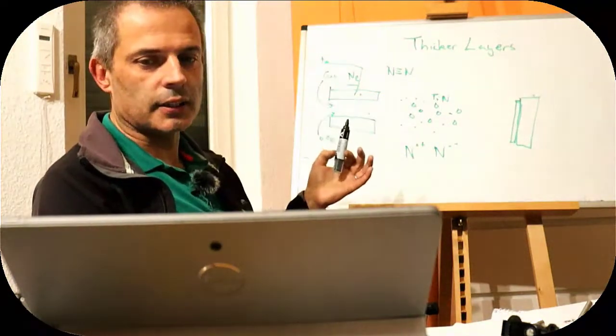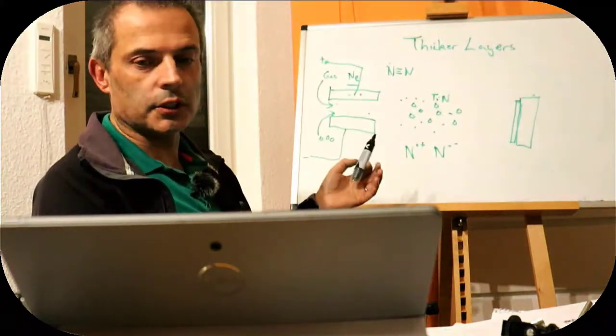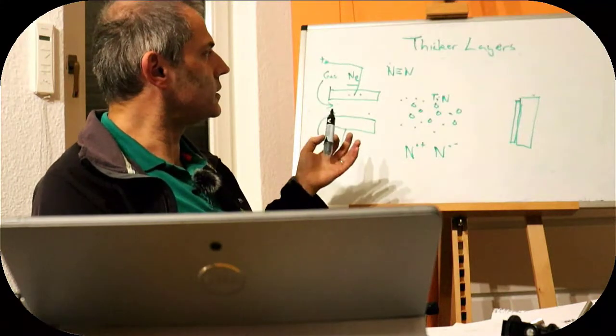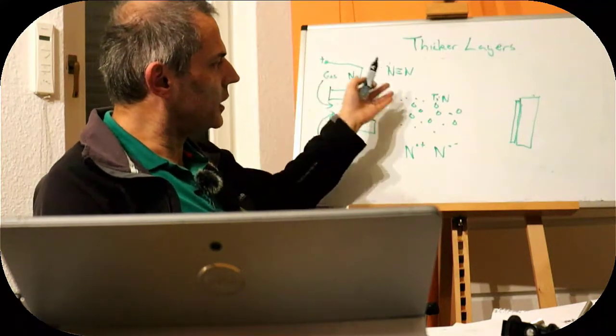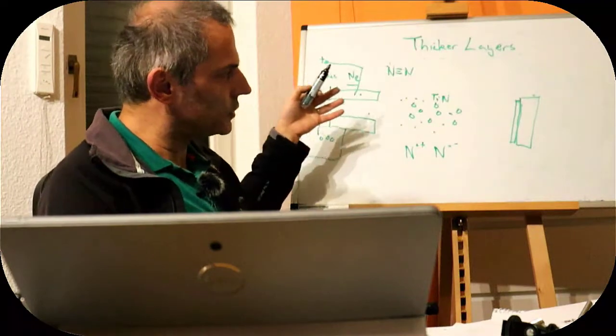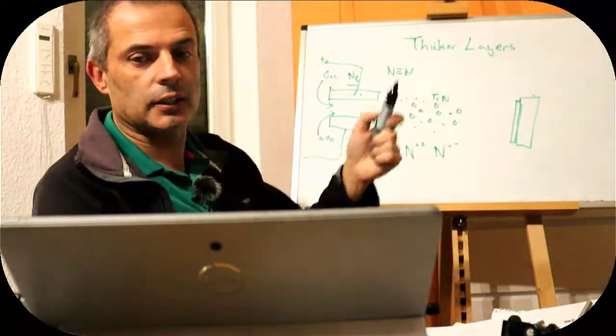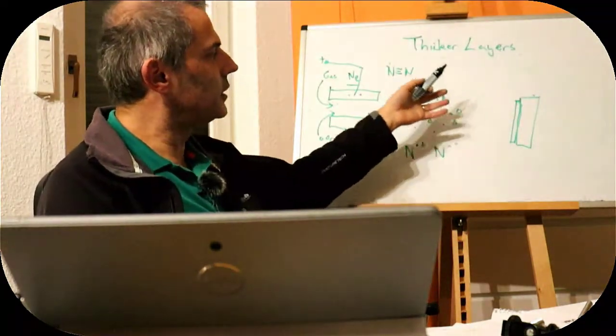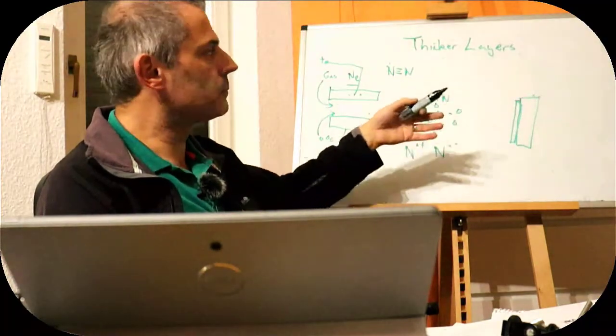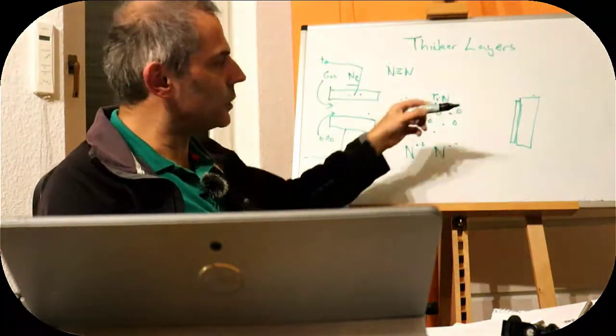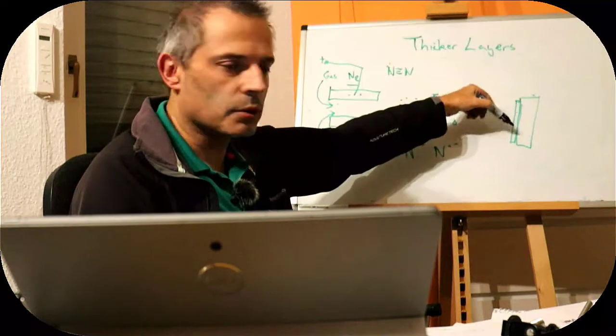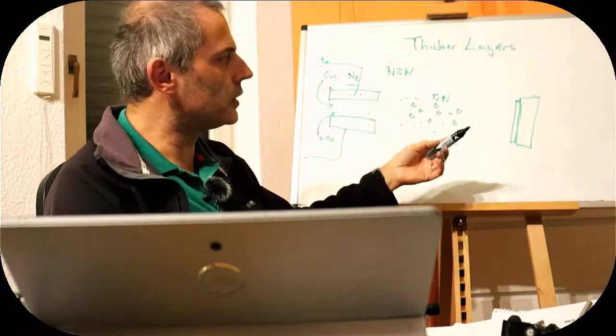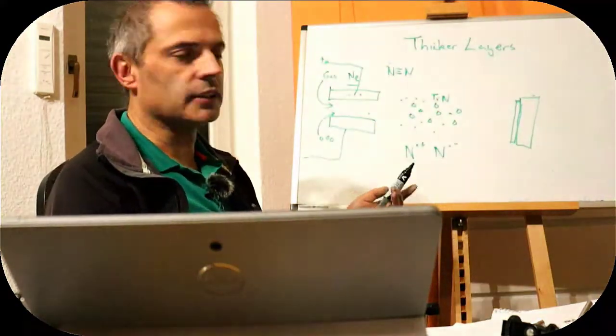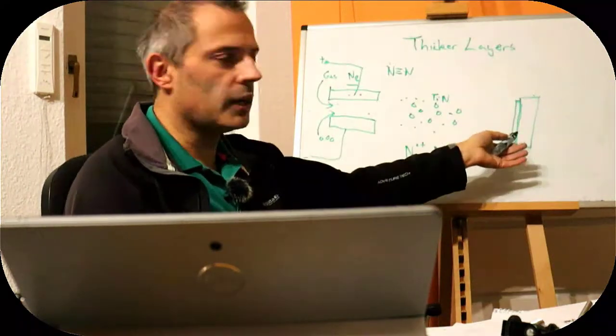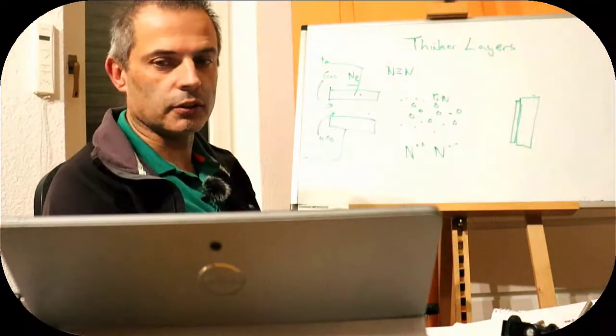The plasma has enough energy because we can put in as much energy as we like. The plasma has enough energy to heat up our titanium nitride and cause it to fly out and melt at the surface at least, and it's pretty hot on the way. That's good because it means that when it hits the surface it will spread out, it will interact with the material behind, and it also means that it has a good chance of getting through any protective layers on the material that we have.